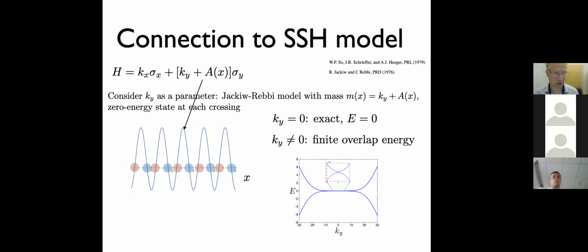And you can also argue the presence of this flat band in this system from the SSH model, or actually the Jackiw-Rebbi model that has been presented a few times already in this meeting. The way to do it is to consider a 1D model where ky here is a parameter of this 1D model, and then this maps to the Jackiw-Rebbi model where the mass is just the ky plus this pseudo vector potential, and this is an oscillating function.